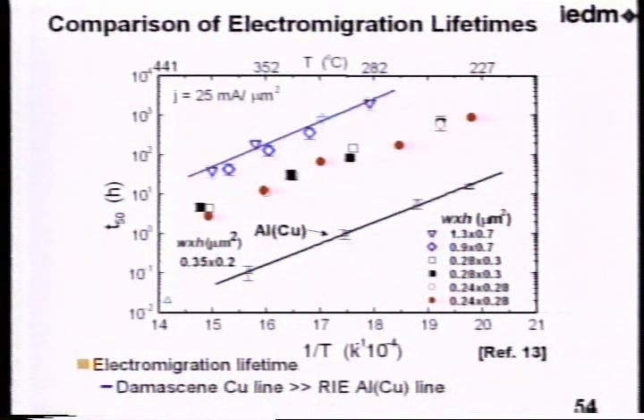This is median lifetime of electromigration against the inverse of the temperature. This is some width by height of interconnect. All the points correspond to a copper interconnect except this line. This is aluminum. As you can see, in this figure, the activation energy of electromigration lifetime is almost similar among aluminum and copper. The activation energy is 1 eV. And if the interconnect area is small, the electromigration lifetime decreases like this. But note that damascene copper line is much bigger than the aluminum line. That's why we adopted a copper interconnect at this moment.